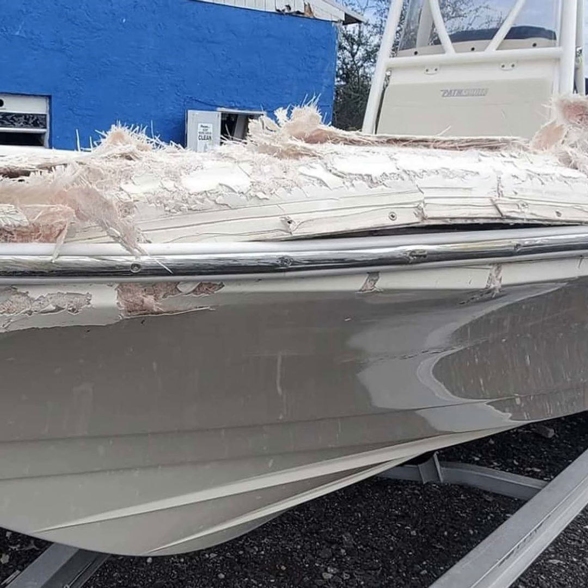Some stress cracks around the transom area are tough. They're kind of on a case-by-case basis. Of course, we'd rather not see any, but it's one of the most common areas to have them. If you're wondering about your transom, we'll probably do a whole episode on transoms, but if you're wondering if your transom's bad, then you need to do a tap test and you can listen to the different sounds. Hopefully you'll have only one sound throughout the whole transom, and it'll be a nice sharp rap when you tap it with your small metal hammer or screwdriver handle or something like that.